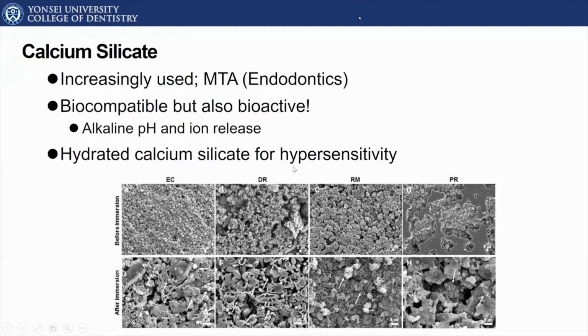The picture down here is the result of interlaboratory studies we carried out with four different MTAs. When they are immersed in simulated body fluid, apatite is formed, an indication of their bioactivity, and perhaps an indication of the regenerative effect that has been heavily investigated for these kinds of materials.